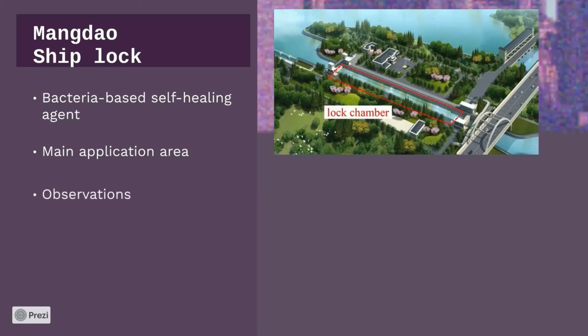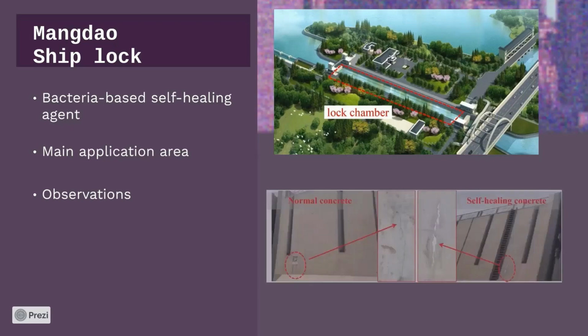The results showed that by adding self-healing agents, no significant effects on the performance of the concrete mixture and the development of compressive strength will be observed. Field observation also shows that cracking was healed after 60 days and leakage was successfully blocked.